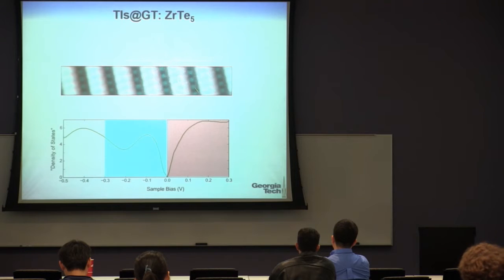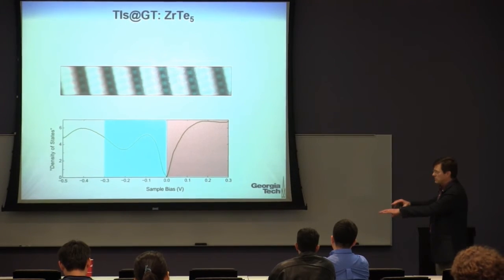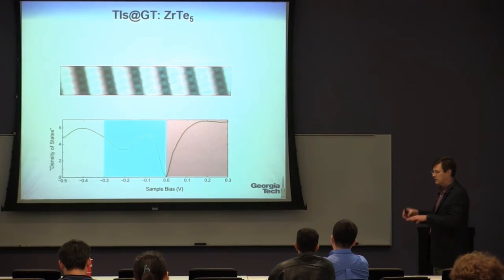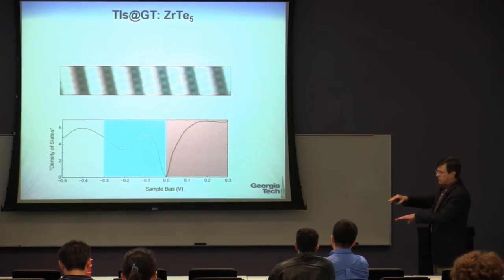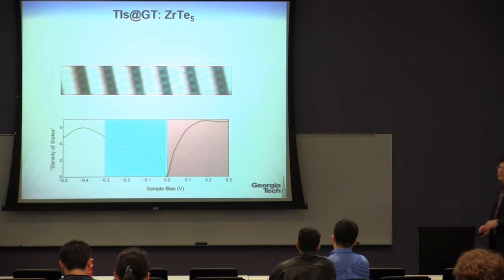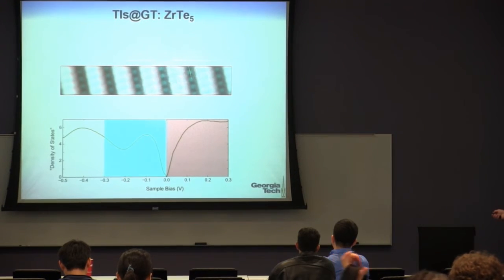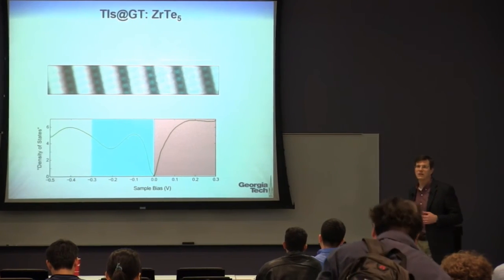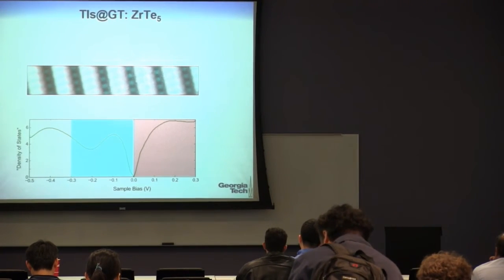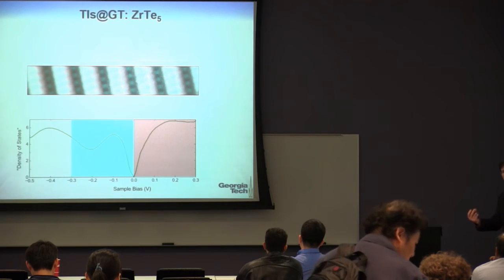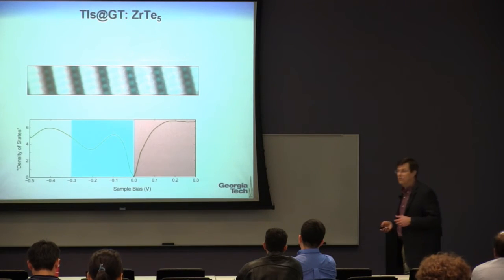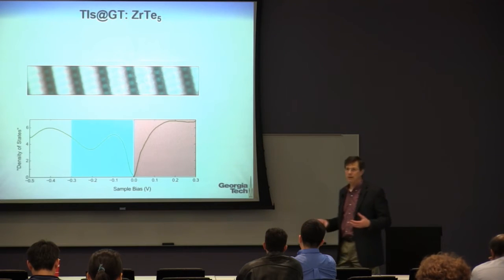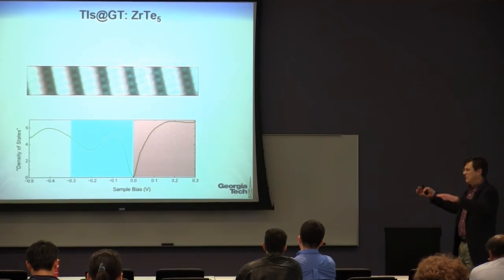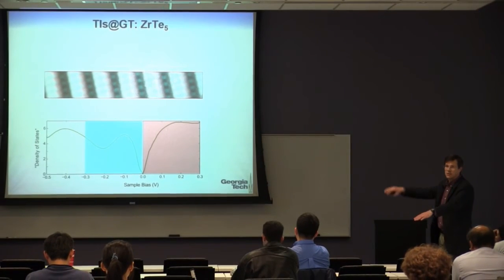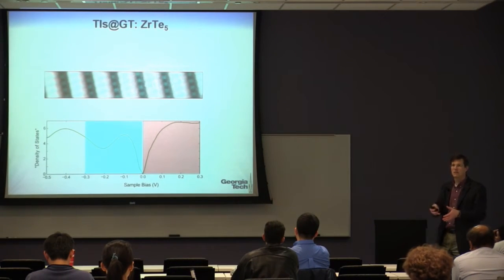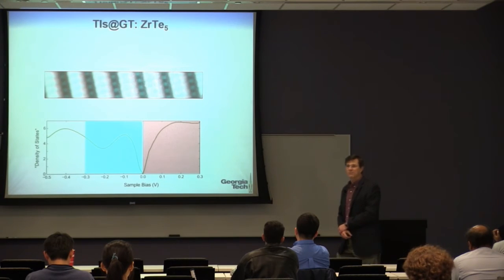What we do find is that when we do get close to a step edge, so these materials they're layers of atoms, right? When you get close to a step edge where I have n+1 layers here and n layers there, you do see a change in the density of states, in particular in this region. And that may be a sign of a topological edge state at the step edge on the surface. Okay. So there may be interesting things that one can do to play with those things from a device perspective. If you take a crystal and you create it at a miscut angle, so then you have an array of these conducting lines, then start connecting them, etc.